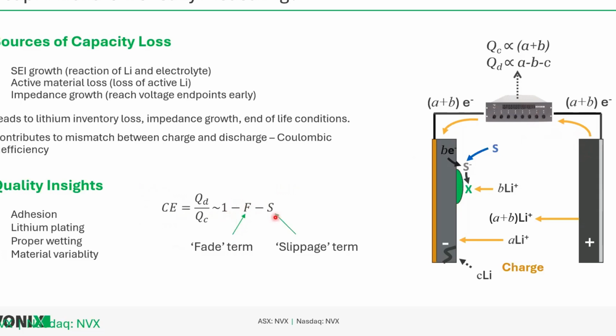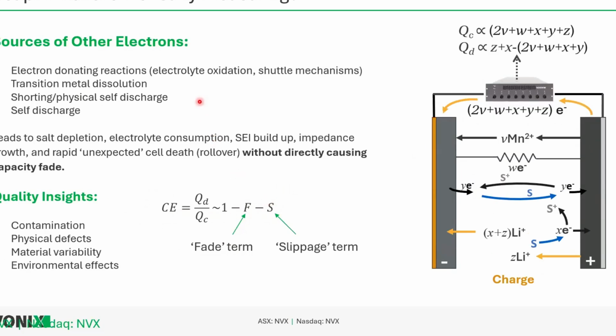But then there are also more electron contributions that we have to think about as well, that are going to make a mismatch between our charge and discharge capacities. What we use as a term to talk about this is we call it a slippage term. This is well documented in a lot of papers dating back about 13, 14 years ago from the Dahn Lab at Dalhousie. And this extra term, making a difference between charge and discharge, is for things like electron donating reactions, transition metal dissolution, things where in order to create charge balance in our cell, if we have a soft short or a short circuit within our cell, when we start to charge our cell, we create this electron shuttle within the cell and we count a bunch of extra electrons.